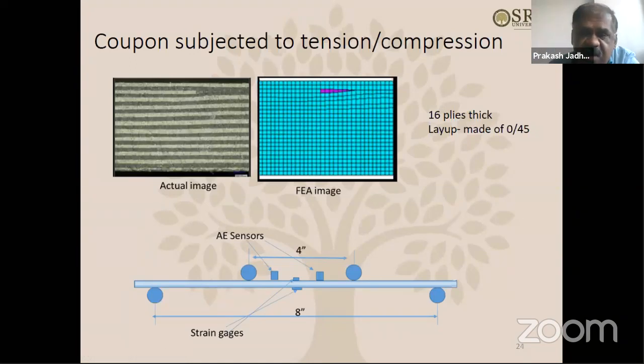So why are these acoustic emission sensors used? Because with strain gauges, basically you plot the load versus strain. But the problem is that the load versus strain plot generally doesn't give you the exact load when the initiation happened. This test is designed such that you apply displacement loading using a UTM, and you measure the amount of load that is resisting. So you are plotting load versus strain, and the plot doesn't really show when the cracks are initiating in the structure.